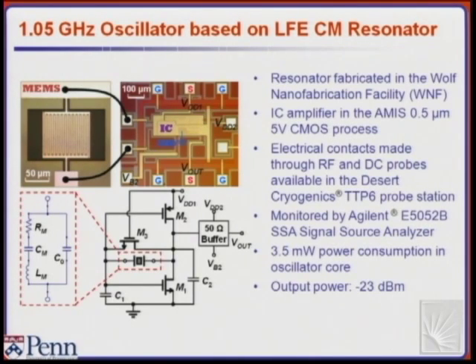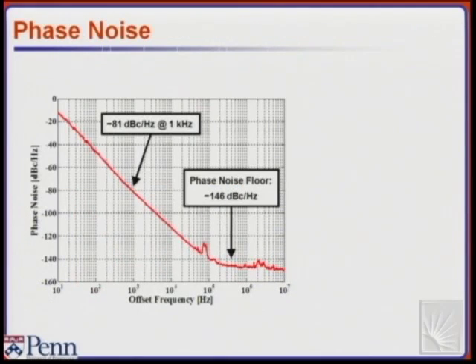And the output power is still relatively low. That was due to some mismatch between the impedance of the resonator and the impedance of the circuit. So we really didn't put all the power that we could have in the resonator, which could have definitely further improved the phase noise performance of the device. We're monitoring the phase noise as a key performance spec of the device using a signal source analyzer from Agilent. And here's the experimental response.